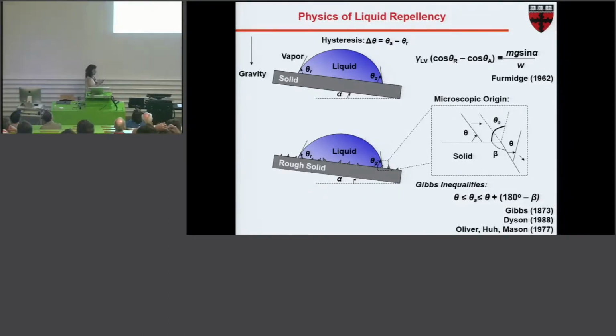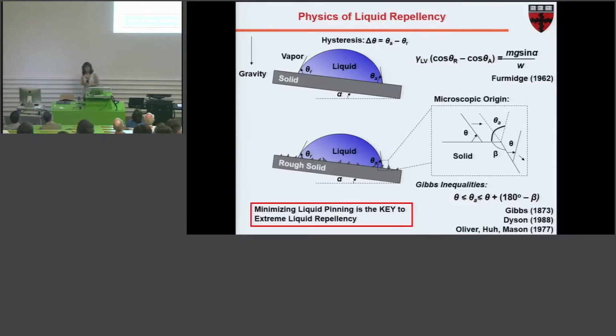This is what actually happens on most surfaces, including superhydrophobic ones: even if you try hard to make the surface as smooth as possible, there are always nano or even angstrom scale defects on the surface, and this nanoscale roughness creates pinning points for the liquid. This roughness, chemical or purely geometric, creates a difference between the receding and advancing angle, and it means that the droplet is pinned on the surface. So maybe the idea is, instead of thinking about how to increase contact angle, as the lotus leaf does, how to decrease contact angle hysteresis, so there is no friction and the droplets can move freely.